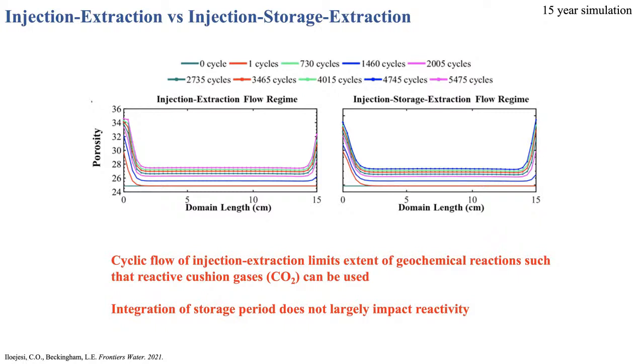And so this suggests to us that potentially we can use CO2 as a cushion gas, even though we know it is reactive. The cyclic flow here is really going to limit the extent of reaction and therefore the extent of porosity increase that we're seeing in the system, which is really favorable for our energy storage operation.